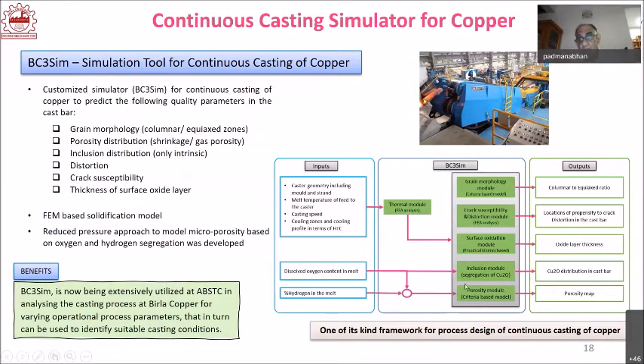And again, the porosity has to be predicted. How is it done? It is by the differential pressure idea. Oxygen and hydrogen, hydrogen usually coming from the fuel, which are there in the copper, get released when temperature is lowered and solidification takes place. So there will be small cavities, which will be empty space because the gas has escaped. Because of the differential pressure, and the thermal gradient which also adds to the stresses present in the neighborhood, there will be a collapse and this will form a crack. So porosity mapping can also be done.